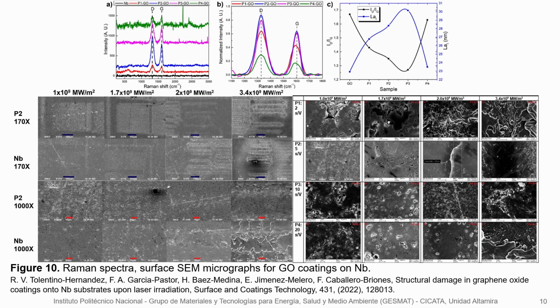Another study is presented where graphene oxide coatings were deposited onto niobium substrates by electrophoretic deposition. They studied the properties of the graphene oxide coatings deposited at different deposition times and how the graphene oxide coatings protect the metal surface against high power laser irradiation. They found that the graphene coatings apparently protect the metal surface from the laser irradiation.